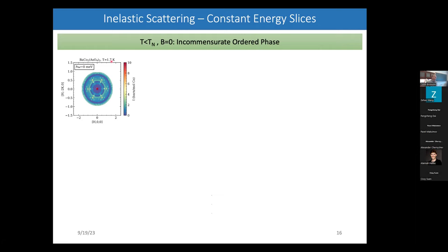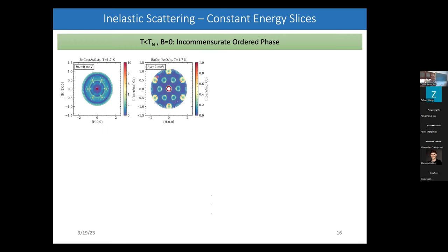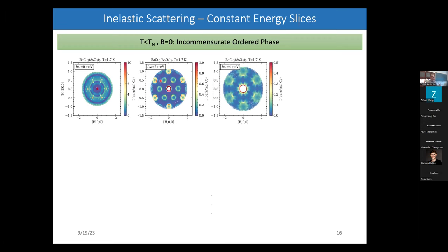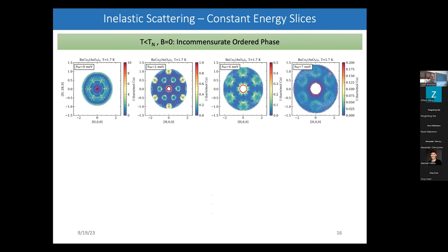First, I'm showing you once again the pattern of the Bragg peaks at low temperatures, and then I'm going to come up in energy transfer to 2 millielectron volts. So now this little set of satellite peaks is no longer visible, but they've kind of merged together to an entire ring of intensity. And then as I come to higher energy transfer, to 4 millielectron volts, the diameter of this ring has increased. And then finally, I end up with these kind of rings all the way up at 7 millielectron volts. And those are the rings around the gamma point where I have allowed magnetic reflections for the ferromagnetic state. And so I'm sort of falling back to what you expect just for ferromagnetic spin waves with this parabolic dispersion around the gamma point.